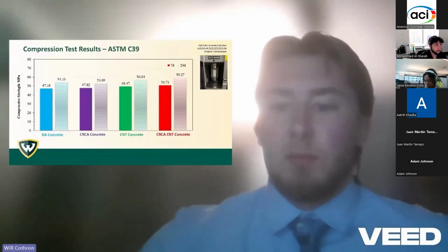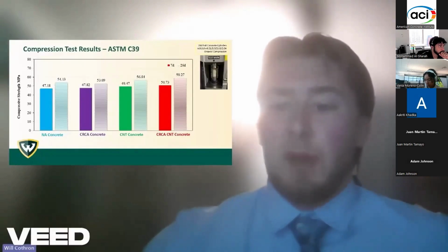When we introduced carbon nanotubes into the mixes, the compressive strength improved notably. This enhancement is due to the CNTs reinforcing the microstructure, making the concrete denser and more cohesive. The CNT concrete mix achieved a higher strength compared to both control mixes and exhibits results similar to those reported